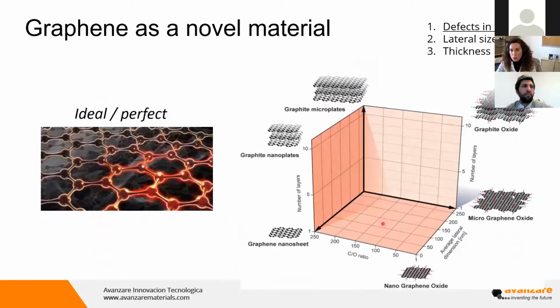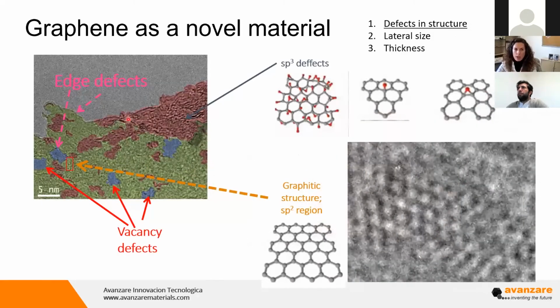I'm going to explain three features of graphene which are really important. These are the defects in the structure, the lateral size, and the thickness. Ideally, all of us, when we read the definition of graphene, think of this perfect honeycomb of carbon with sp2 hybridization. However, when we prepare graphene, the reality is that we have some defects due to different process aspects. So what we can see when we analyze the surface of a layer of graphene is that, of course, we have this perfect zone in the green region with these graphitic structures where electrons and photons can move easily, but we also have these regions with defects.